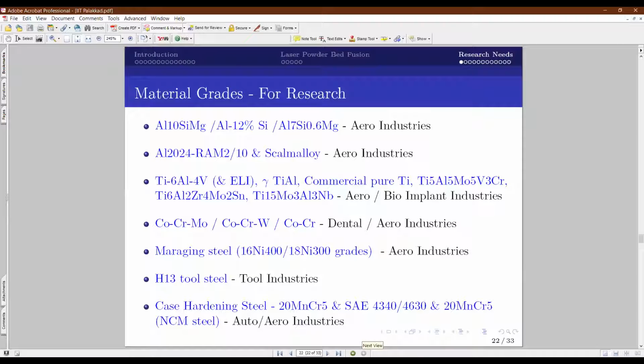Coming to the titanium alloys, these powders are available worldwide from the powder manufacturers for 3D printing. Titanium 6 aluminium 4 vanadium, gamma titanium aluminide, commercial pure titanium, and titanium, aluminium, molybdenum, vanadium, chromium. This is a kind of alpha beta titanium alloy. Then titanium 6242, again an alpha beta titanium alloy. Then the beta titanium alloy called titanium 15 moly, 3 aluminium and 3 niobium. This titanium is very popular in the compressor sections of aero engines, and some bio implants are also made from it.